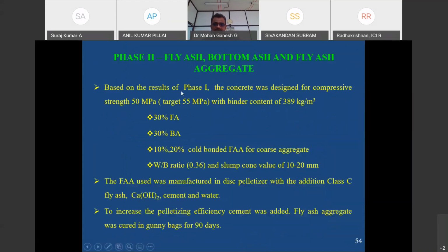Now in this, again we have divided our work into multiple phases. Our target compressive strength is 55 MPa, so easily we can achieve 50 MPa with a binder content of 389 kg per meter cube. In this, we have replaced 30% fly ash, 30% bottom ash, and 10% or 20% fly ash aggregate. And for comparison purposes, we have maintained a constant water binder ratio as well as slump value. Here, for the fly ash, we used class C fly ash and a small quantity, I think 2%, of calcium hydroxide plus cement as a binder to make the pellets. So for improving the pelleting, we have added the cement. And all the manufactured aggregates were cured up to 90 days in gunny bags.